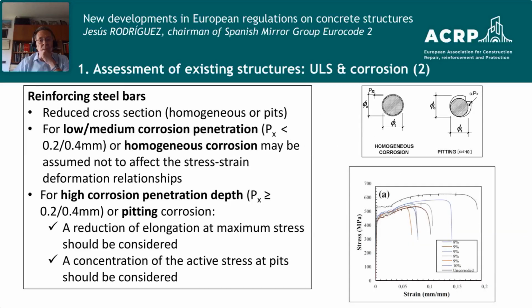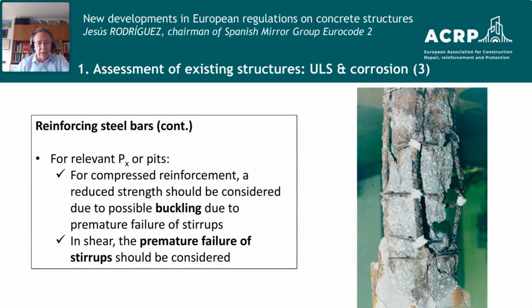In the case of steel, we need first to consider the reduced steel cross section, either in homogeneous corrosion or in concentrated pits. And then we also have to deal with some recommendations about the stress-strain relationship. If there is a low level of corrosion, and perhaps this is the last draft version that has been distributed, or homogeneous corrosion, we can consider that there are no relevant modifications in the stress-strain behavior. However, if we have high corrosion penetration depth or pitting, we need to consider some reduction at least in the elongation at maximum stress, and also to consider some active stress at pits. But these are only general considerations.